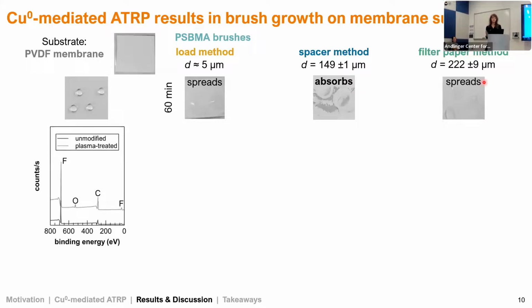So to further confirm the presence of our brushes, we also looked at XPS results. This gives us the surface elemental composition of our samples. This shows the unmodified membrane in the darker gray, and we also have the unmodified membrane after plasma treatment in the lighter gray. We see peaks here for fluorine and carbon, that's associated with PVDF, and we also see a small oxygen peak after plasma treatment.